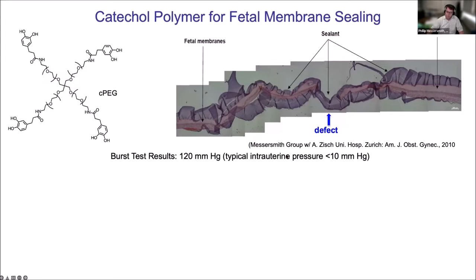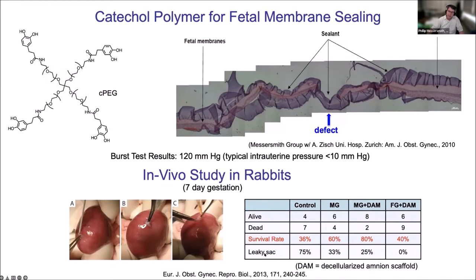We also conducted an in vivo study in rabbits where we showed that the survival rate of rabbit fetuses was increased from 36% if you just do the puncture and do nothing. 36% of the fetuses survive, and we could increase that to 80% with our adhesive plus basically a little plug that we glued in with our adhesive. So from 36 to 80%, very promising.